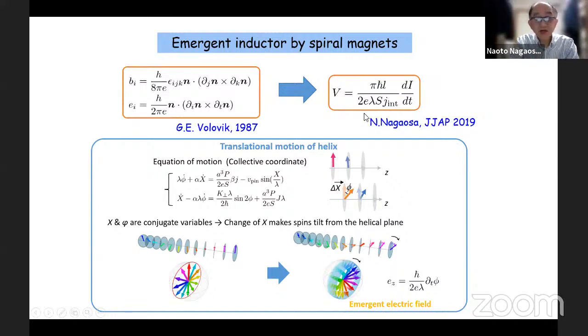So this capital L, namely the inductance, is inversely proportional to lambda. So if you have a very short pitch helical structure, then you can get a very large inductance, which is very useful for application. And also, this S is the cross section of the sample. So as you have a very small cross section, the inductance can be bigger. So first we need to develop some materials which show a very short pitch lambda.